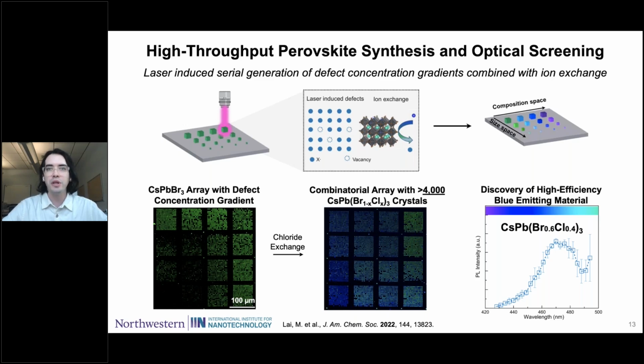So for doing high throughput screening, we now need to tune lots of different compositions of the perovskite in a single array. And so what we can do is pattern a library where every perovskite particle is identical, and then go through with a laser and shine the laser at each individual crystal one at a time, just for a couple of seconds. And as you shine the laser, you induce loss of some of the ions. In this case, we're inducing loss of bromide ions. And then the extent of irradiation correlates with the extent of defect generation. And so after we introduce defects, we can then submerge the perovskites into, in this case, a chloride solution, and those chloride anions will now be introduced into the defect locations.